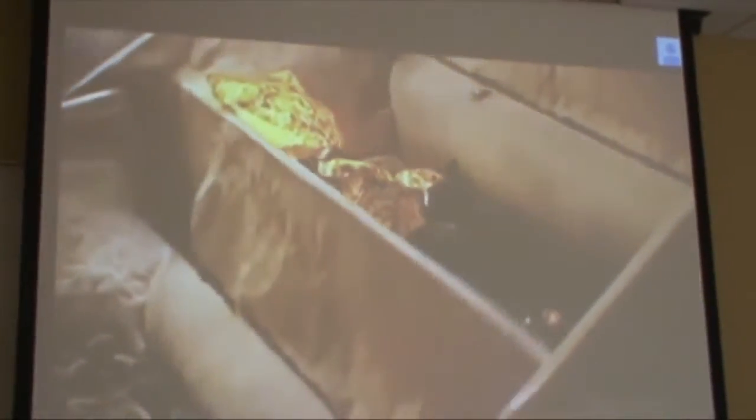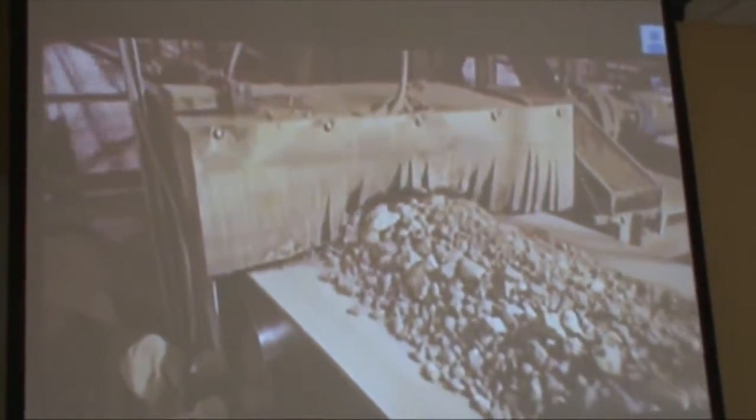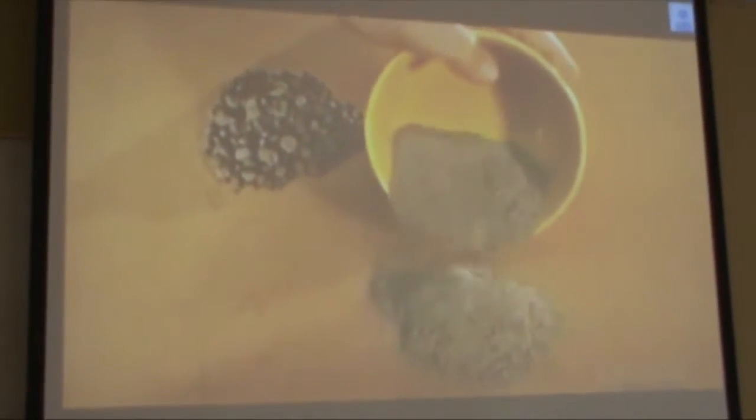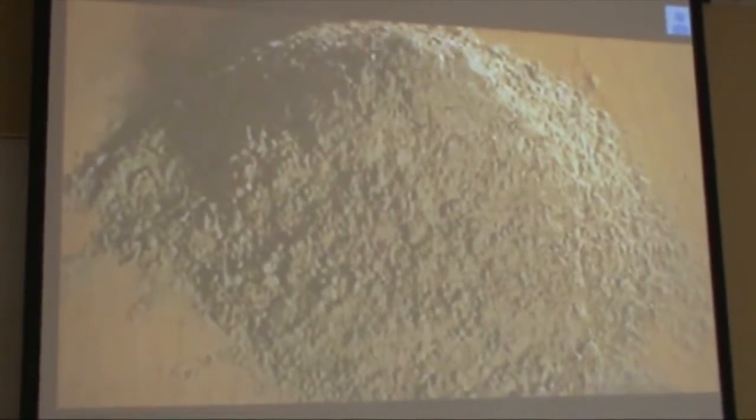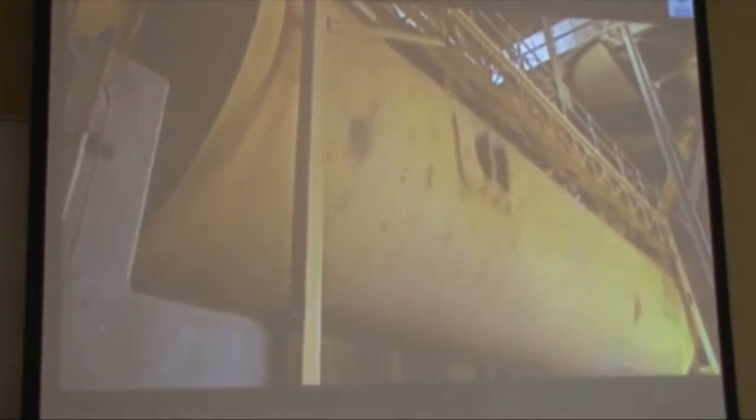As the clinker leaves the kiln, large fans cool it down to between 60 and 80 degrees Celsius — it's important to cool it quickly for quality cement. The last stage is finish grinding: gypsum is added to the clinker, and cement mills called ball mills (containing about 150 tons of metal balls in the largest mill) crush and grind the clinker and gypsum into a fine powder.